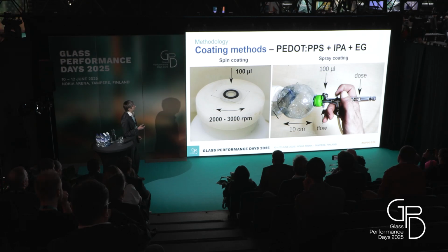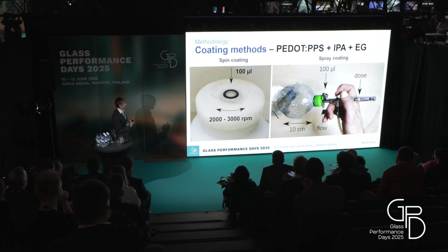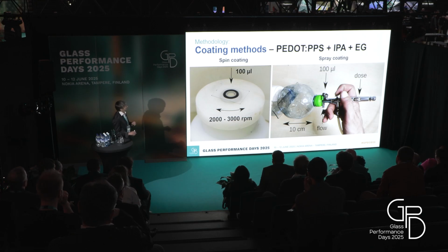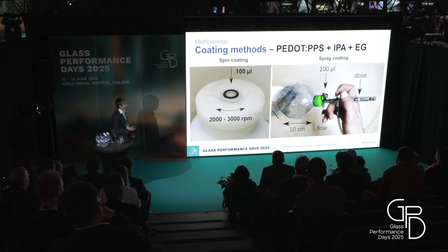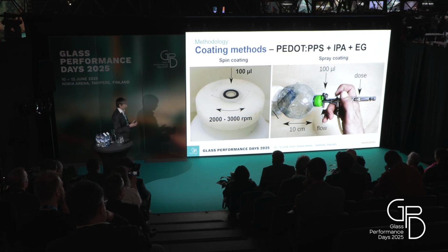And afterwards, we plasma treated flexible glass. I treated it with two methods. One is spin coating, which rotates the sample, and I just cast the drop on the sample, and it spreads on the surface. And the second one was using the dual action airbrush, which also needs a very similar dose of the amount needed for covering the same surface, so they were comparable methods.